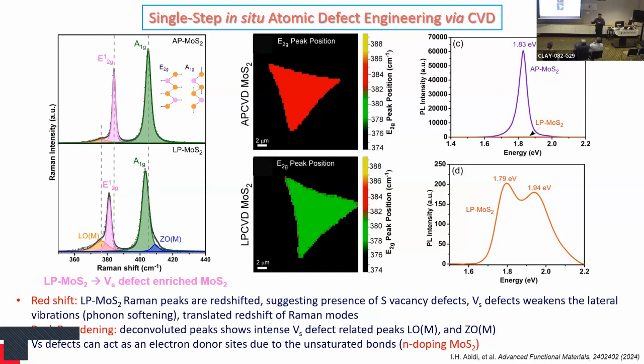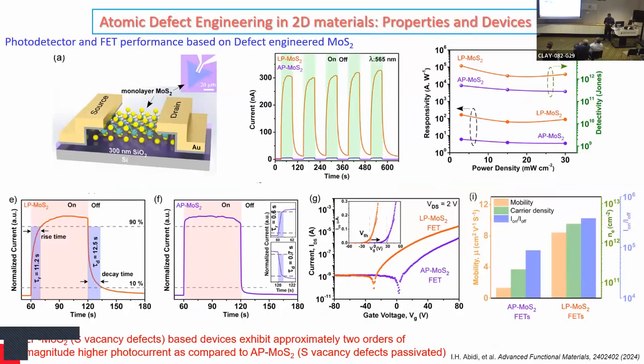If you have oxygen in the environment, like oxygen passivation in the atmospheric pressure CVD condition, the sulfur vacancies are passivated with oxygen, so it shows similar behavior to what ideal MoS2 should look like. However, whether you want oxygen passivated MoS2 or sulfur vacancy MoS2, both have their own characteristics, and both can be used for different purposes.